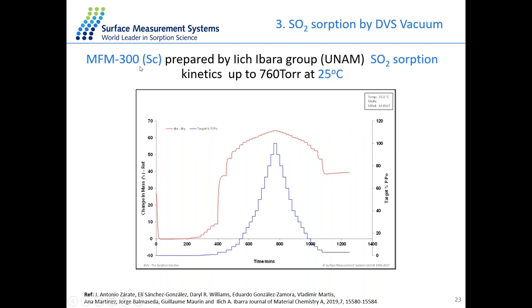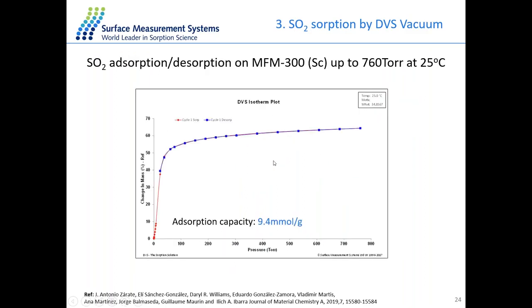So here, as an example, we have the sample MFM 300, the MOF material provided by UNAM from Mexico. And we're focusing on the SO2 sorption at 25 degrees up to 1 bar. We set up the experiment with different stages. The concentration of SO2 is from 0 to 100% with 5 or 10% intervals. And that's the mass plot of the SO2 sorption.